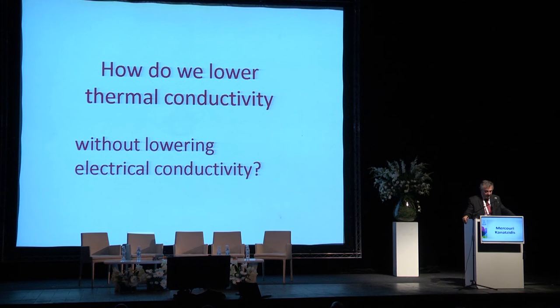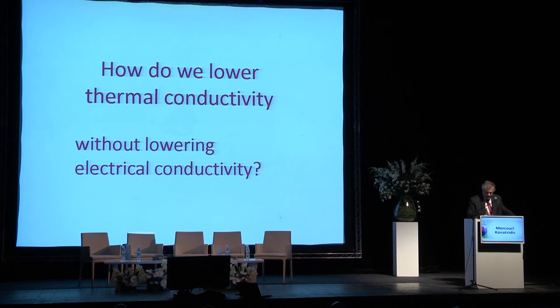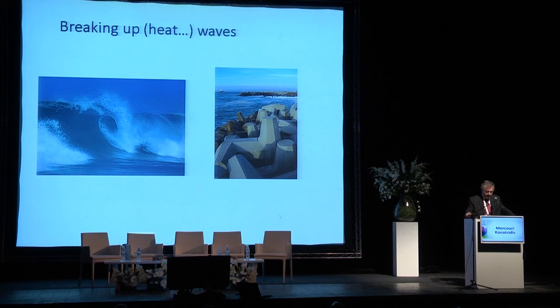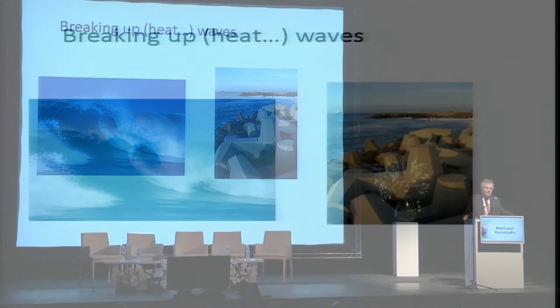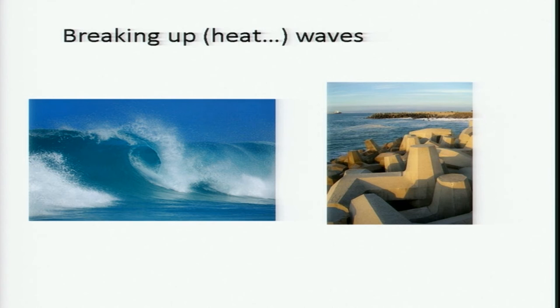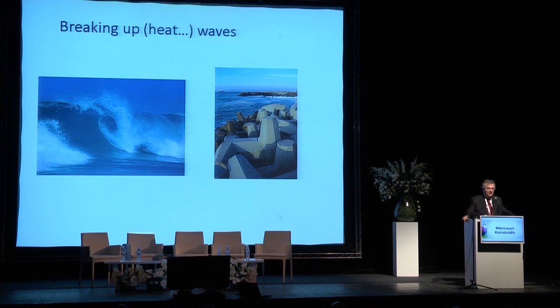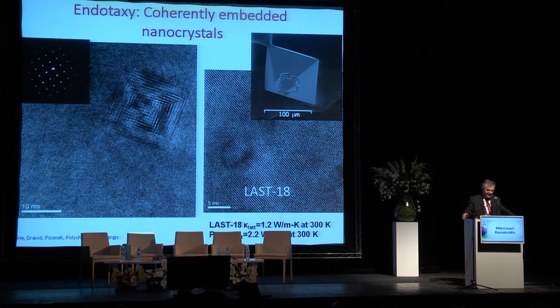But how do we lower thermal conductivity? That was quite challenging. How do we lower thermal conductivity without hurting the electrical conductivity? So what is heat? Heat is waves of vibrations of the lattice. So waves inside the lattice go from left to right, transporting heat from left to right. So how do you break up a wave? That's where nanostructuring came in. For example, if you want to break up waves, you put in small artificial islands in front of the harbor. And you make sure that the dimensions of those barriers are close to the wavelength of the wave coming in. So, thinking similarly, we were able to put such barriers inside the crystals.